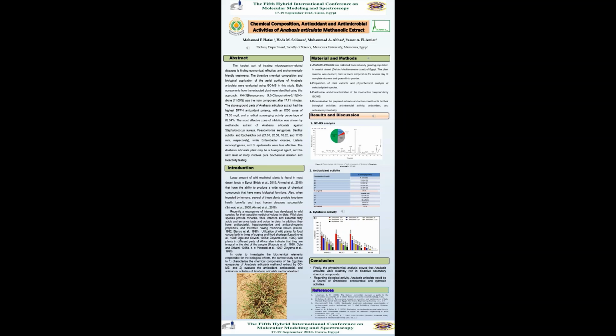components categorized as fatty acids and esters, 57.78%, hydrocarbons, 23.89%, steroids, 14.84%, and terpenes, 6.46%. Antioxidant activity. According to the results, the extracts of Anabasis articulata exhibited antioxidant activity in a dose-dependent manner, P less than or equal to 0.05, which was comparable with ascorbic acid as a reference standard.